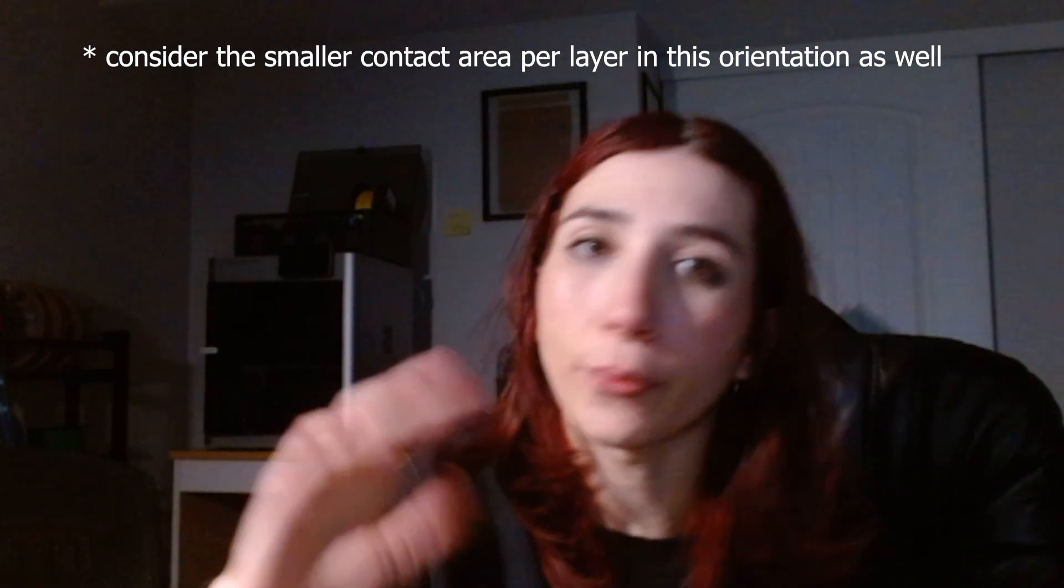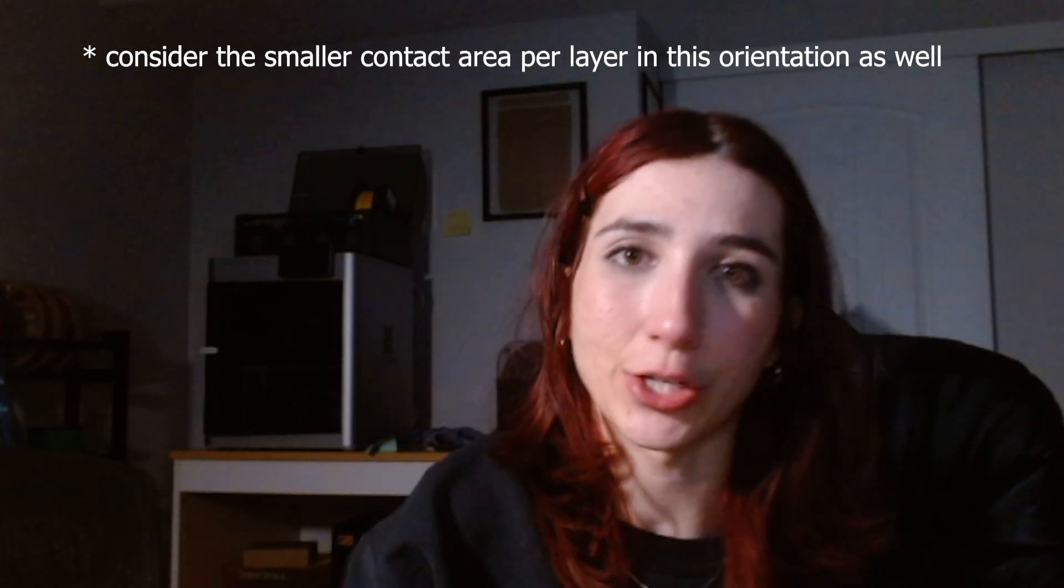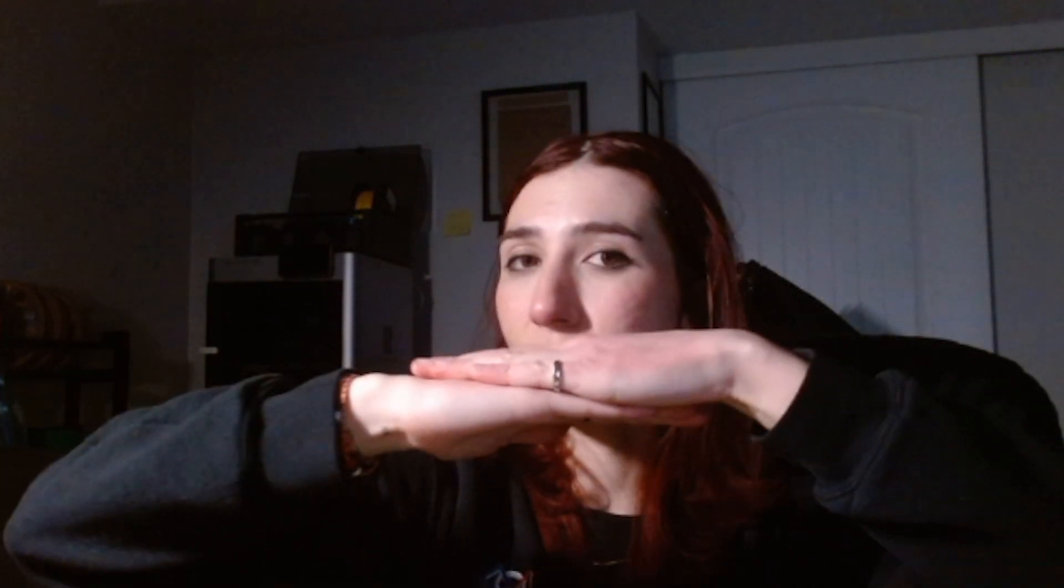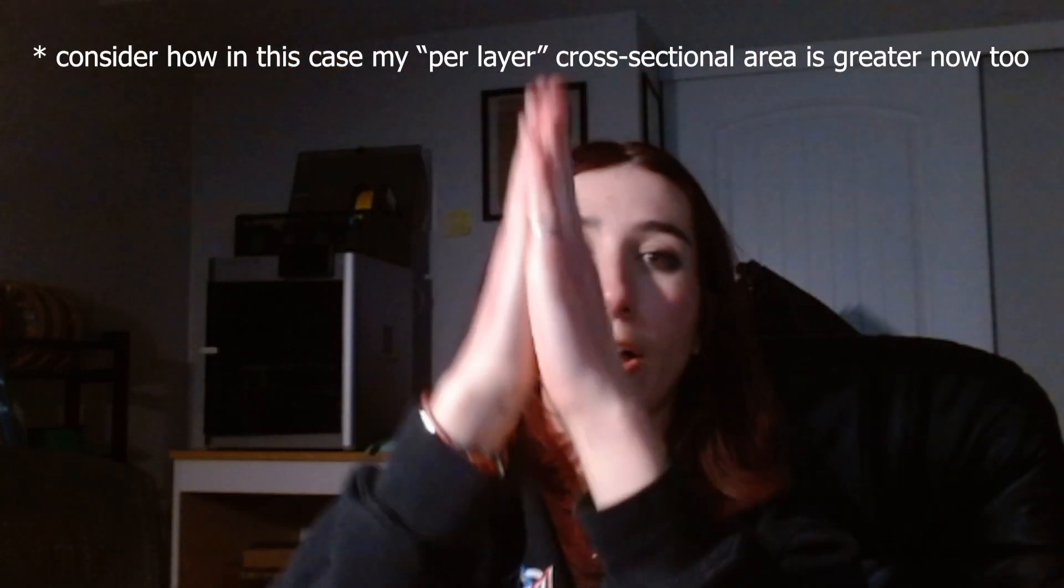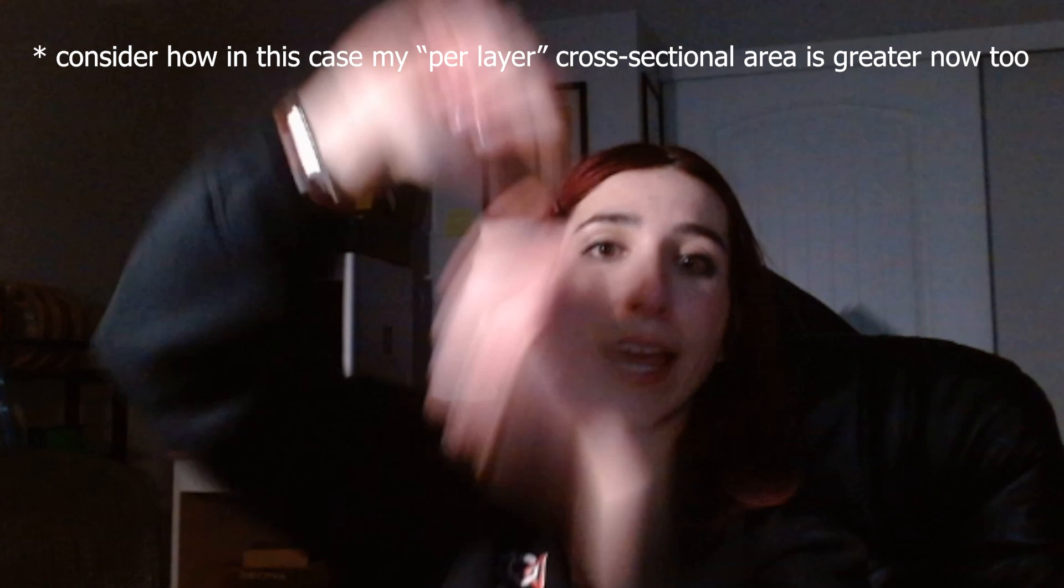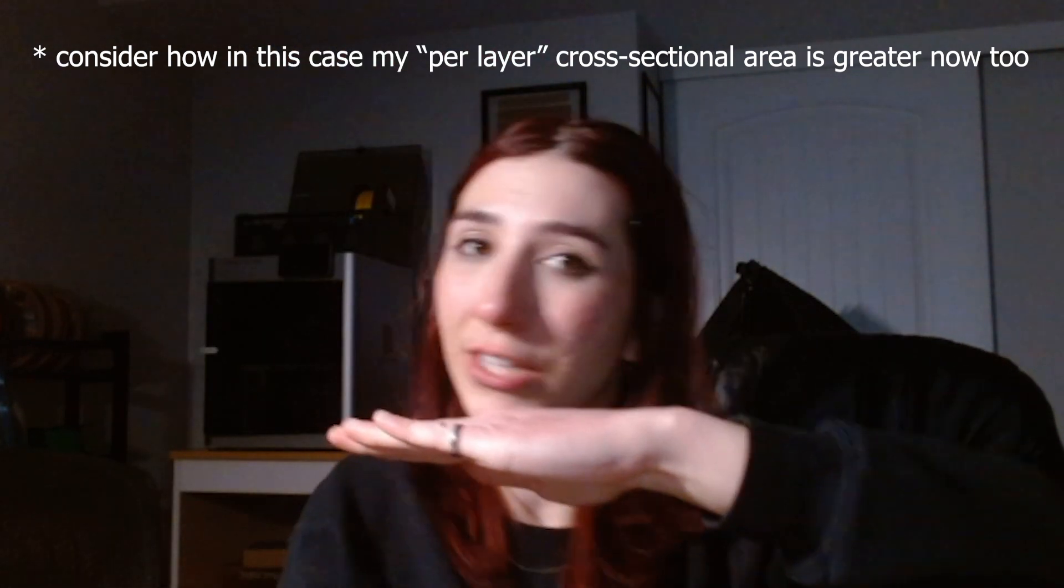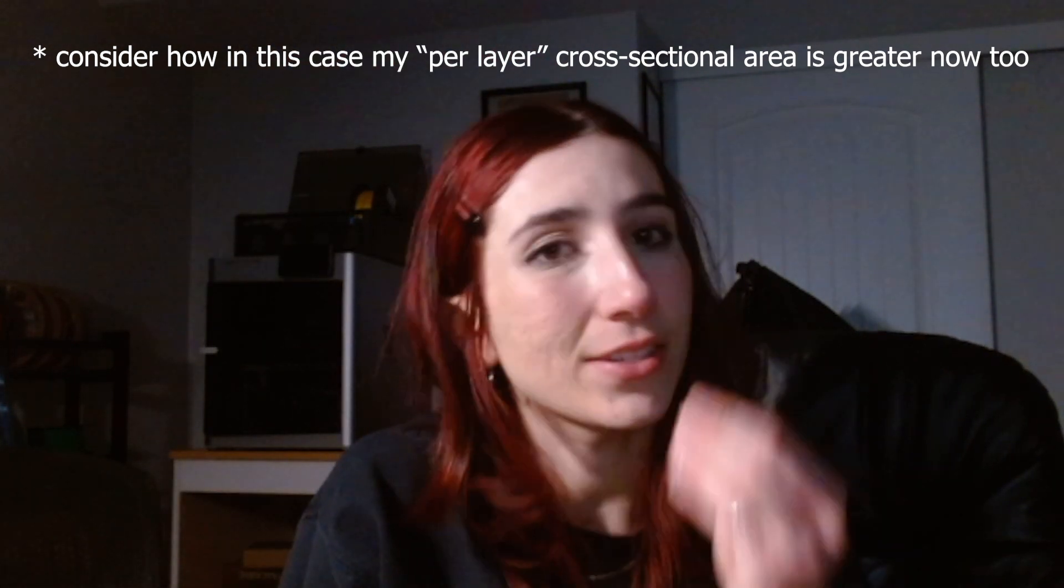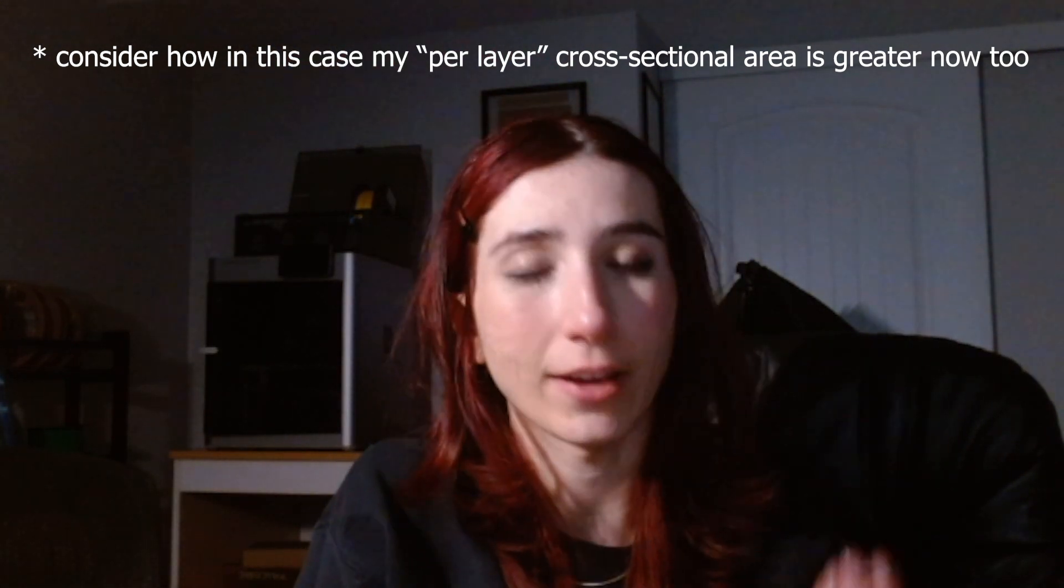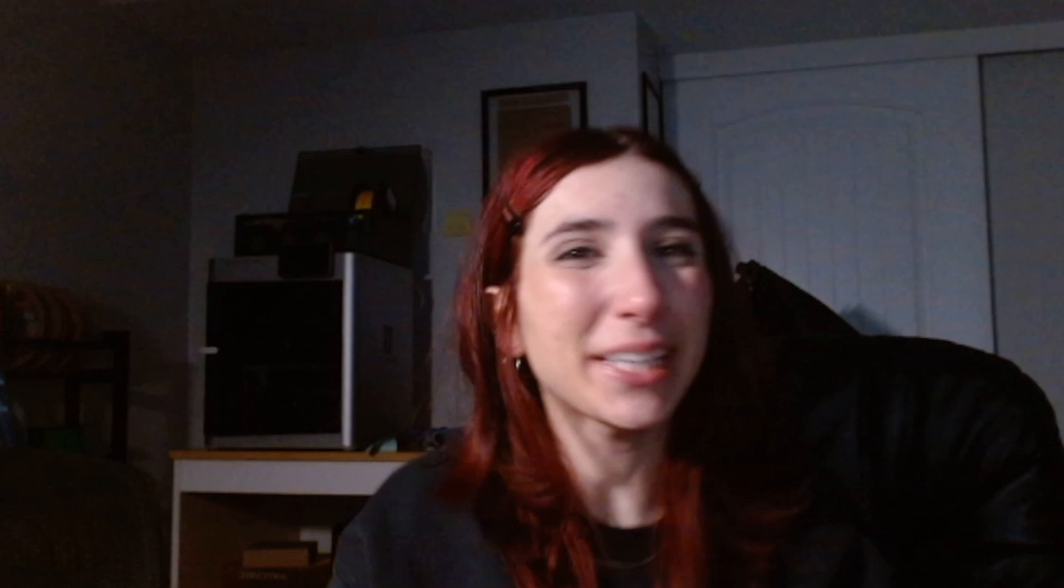Now, that's probably going to be our weakest orientation for tensile strength, but if I print a piece fully flat on the build plate with the layers going longwise like this, then I flip it up like this and pull it in my tensile machine. Now instead of relying layer by layer like this on this interlayer strength, I'm working along the layers, and the on the build plate orientation will give me the greatest strength of that sample.